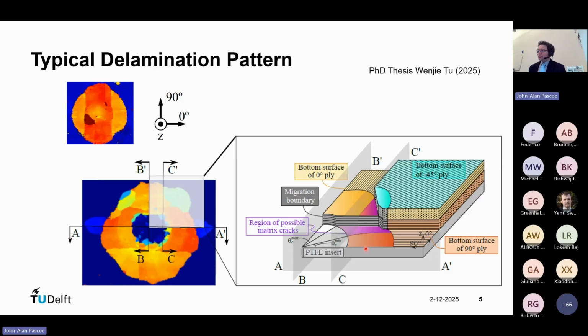And so what you see is an area where the delamination is happy to keep growing where it is. And you mainly see these fiber imprints, maybe some cusps. Then you see an area where you really see matrix cracking. So the delamination appears to be trying to migrate, but it's then being blocked by the surrounding fibers until it eventually can break through. And then over here, it immediately migrates and then continues smoothly in that plane.